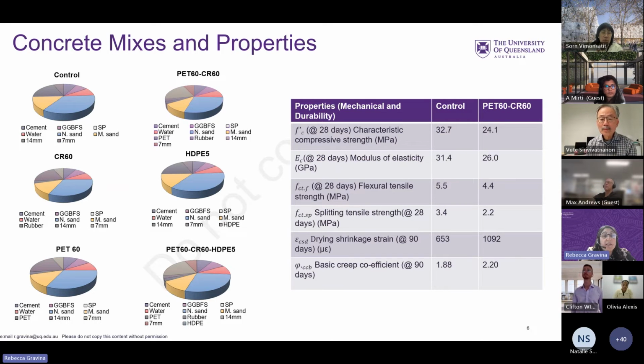So it's well known that as we replace the natural aggregates with recycled material content, in particular crumb rubber and PET plastic, we do get a reduction in the mechanical performance. So we do get a reduction in the compressive strengths and the modulus of elasticity, the flexural and tensile strengths, and the durability properties do get affected as well. But the important thing is to what extent do they get reduced, and if those mechanical and durability properties are still within acceptable limits, and do they still allow this type of concrete mix designs to be used and applied in the field. So I haven't got time to present all the results, so it's just a snippet of some of the results that have been achieved.